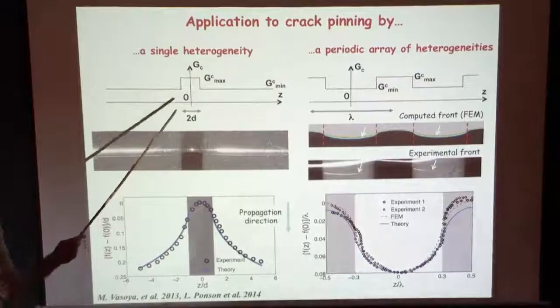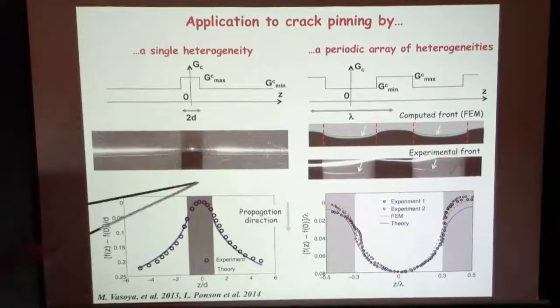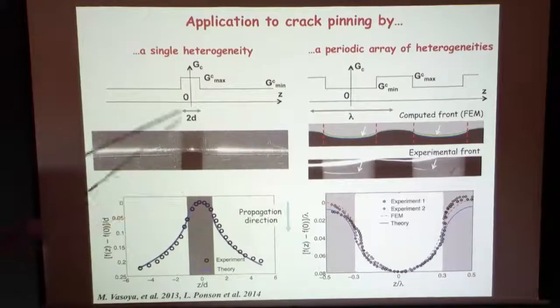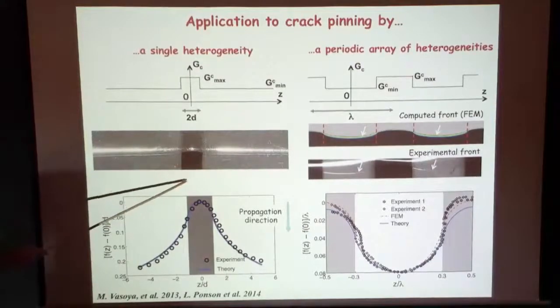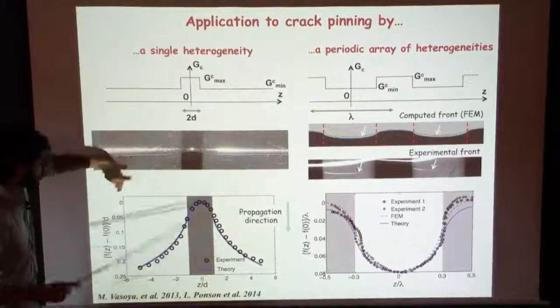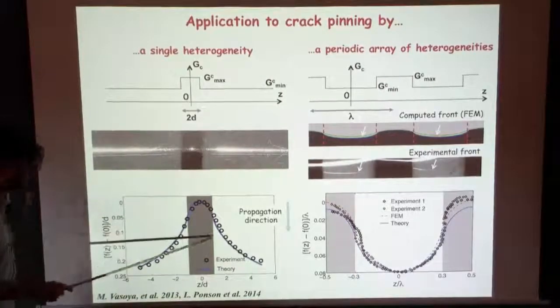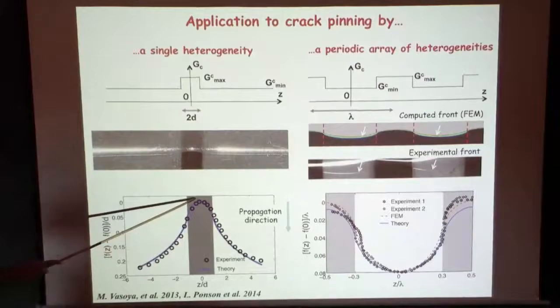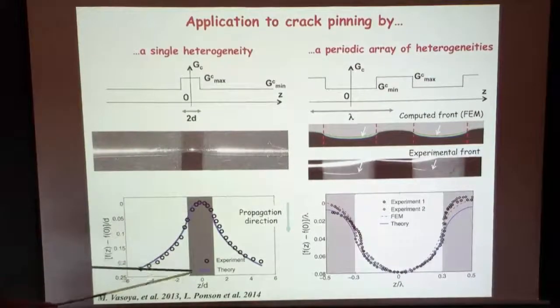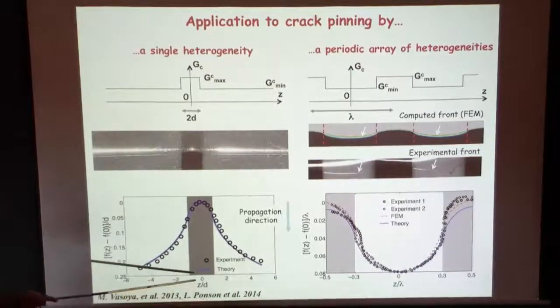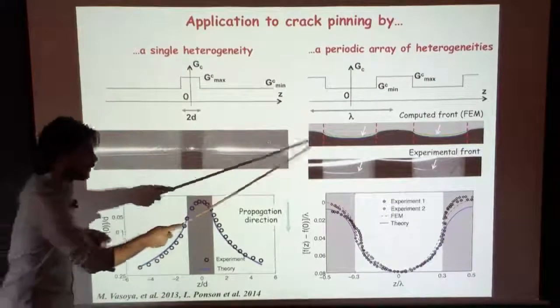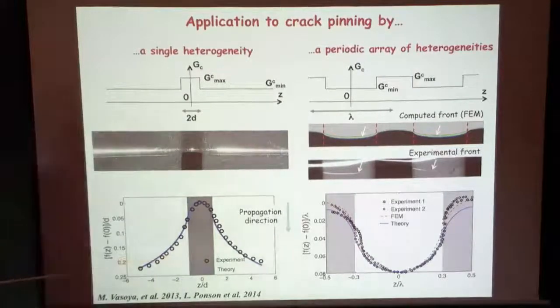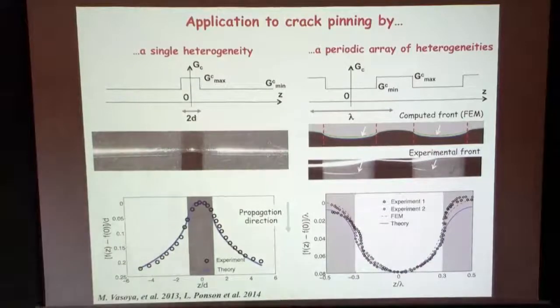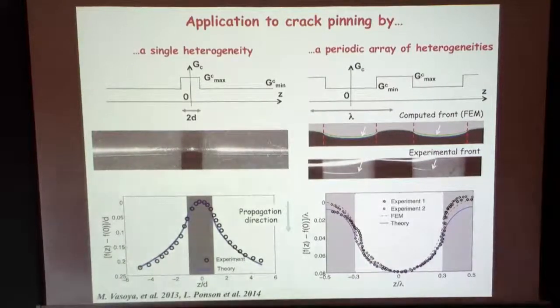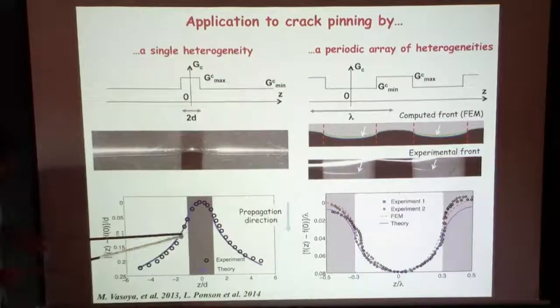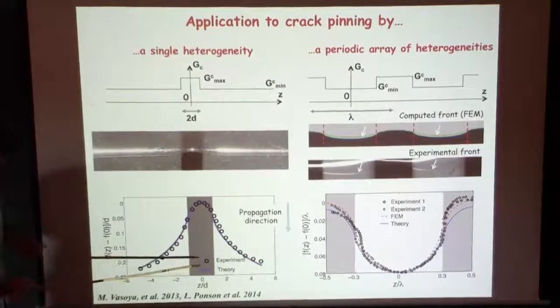So I have two examples. The first one is if you introduce one defect of larger fracture energy in the middle of your sample, you have propagation this way. So at this point, the crack is late, and you can measure the perturbation, the black dot, and compare with the theory. Here in this system, we control defect toughness. We print a defect with a well-known value of fracture energy, so we can really test quantitatively the prediction of the model.